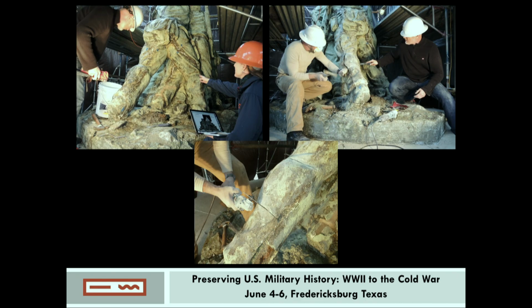As indicated by the X-ray survey and visual assessment of the surface, after all coatings had been removed, 71 areas needed to be opened up. And we were asked to give a per square foot estimate, but it has volume, this sculpture. It proved to be absolutely difficult for us to do that because one area was related to the next, and it was really hard to do that. So we ended up joining a lot of areas together, and we had to do that in order to access